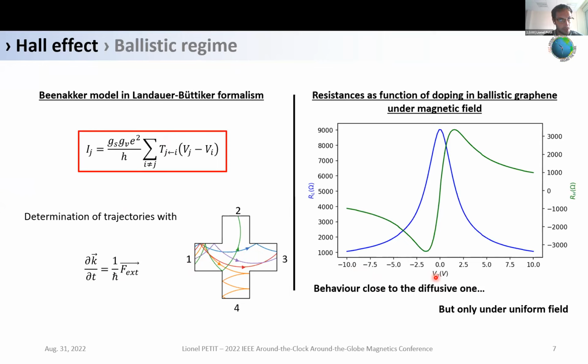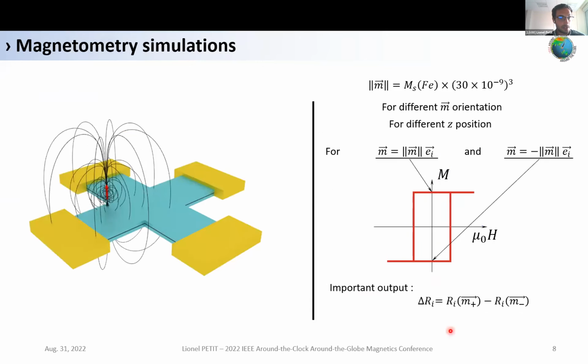But most of the time, when we want to make magnetometry on a nano object, we have to deal with a non-uniform magnetic field. And that's why I made a lot of simulations in both diffusive and ballistic regime. And I simulated a Hall cross, and I displaced a dipole on top of this Hall cross to see where to put it to have a good signal.